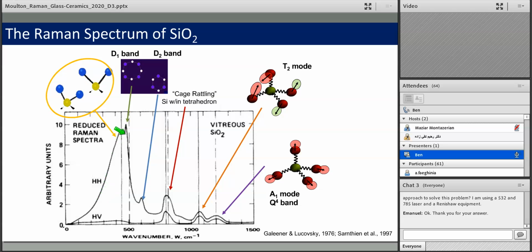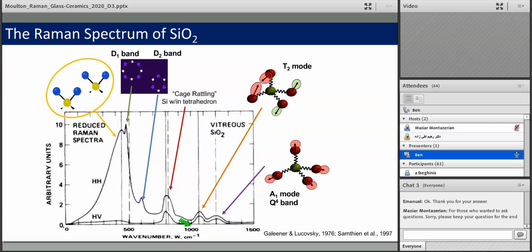At increasing wave numbers, we see two sharp features, these guys here. The consensus in the community, and this is just defended by simulations of Sarnthein in 1997, is that these modes correspond to the breathing modes of three-member and four-member rings. These are tetrahedra of silicon and oxygen between them. And in the four-member ring and the three-member ring, all the oxygens move away from the central silicon.